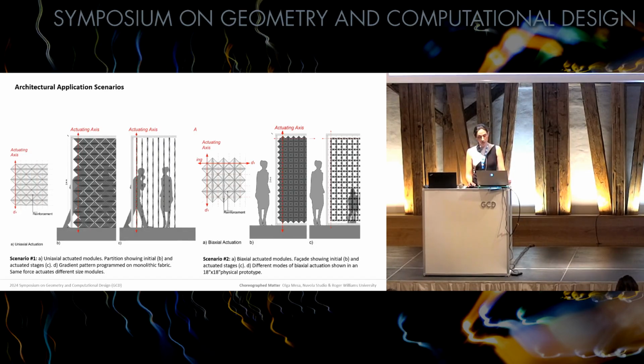Here, tessellations were generated by patterning a single monolithic composite fabric to achieve varying degrees of porosity and change in three-dimensional shape. The adjustable surfaces were actuated efficiently by reducing the number of actuators per module and instead actuating uniaxially or biaxially on an array, producing different degrees of porosities. These were reversible in a matter of seconds once the force was not applied.